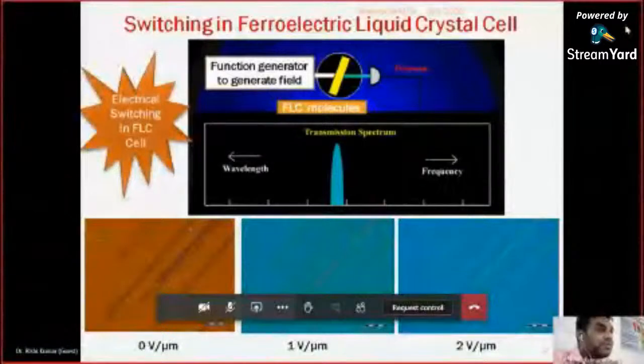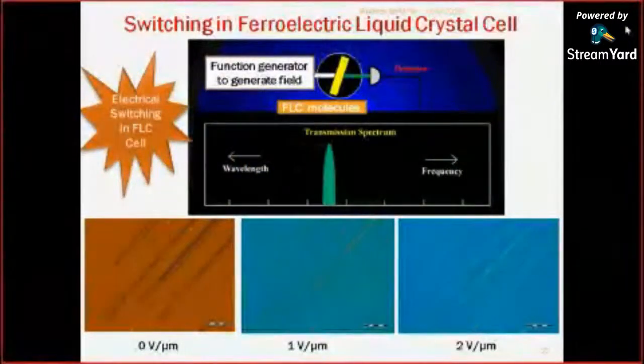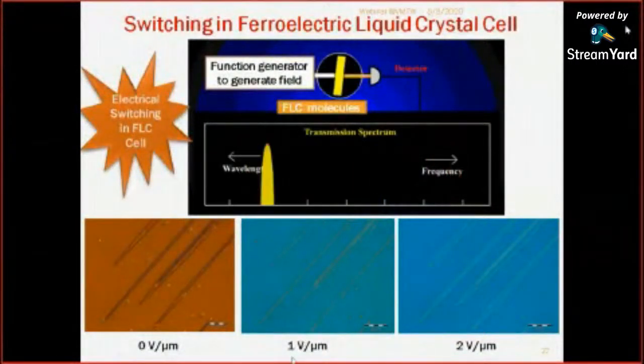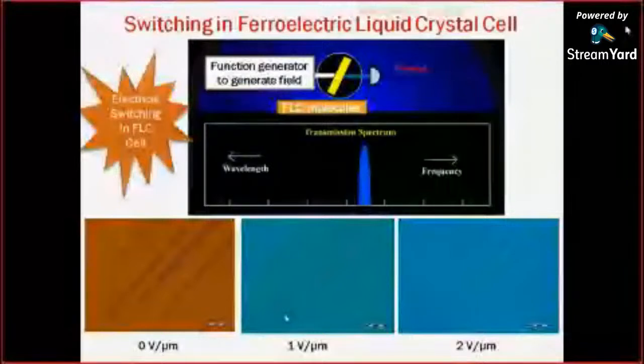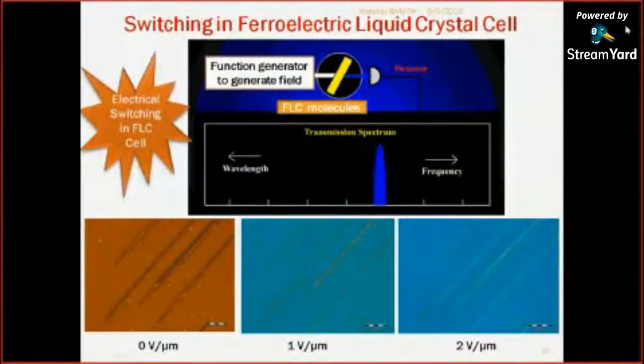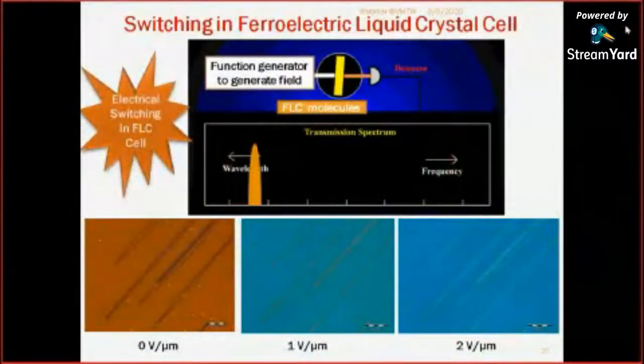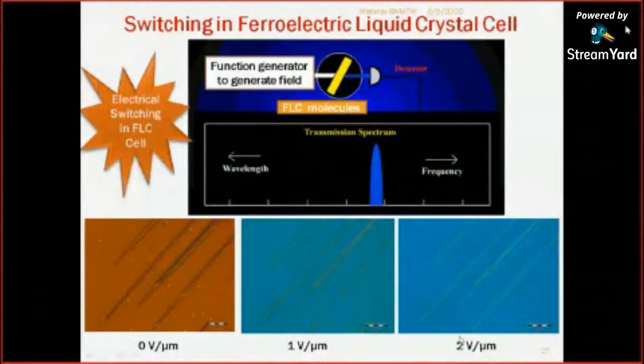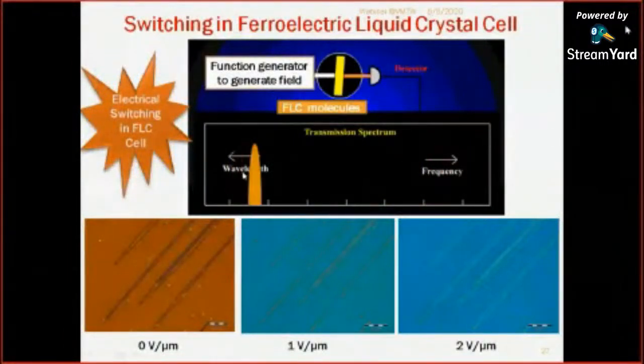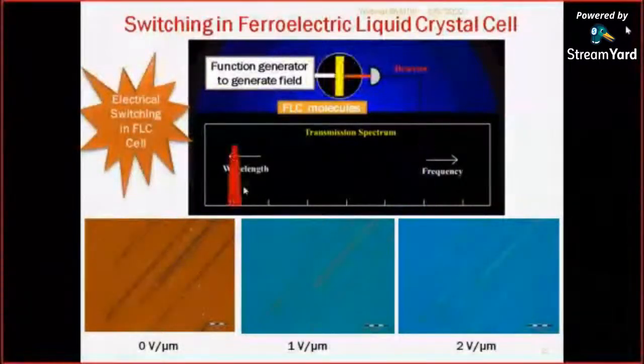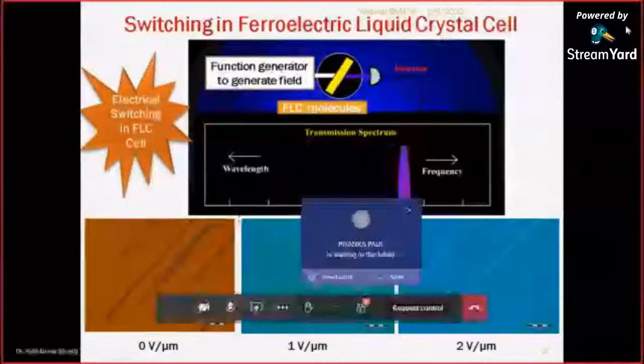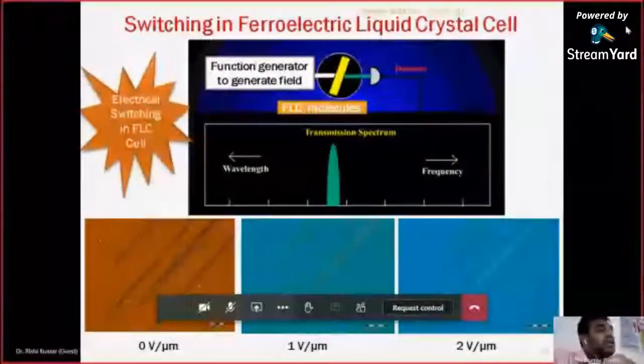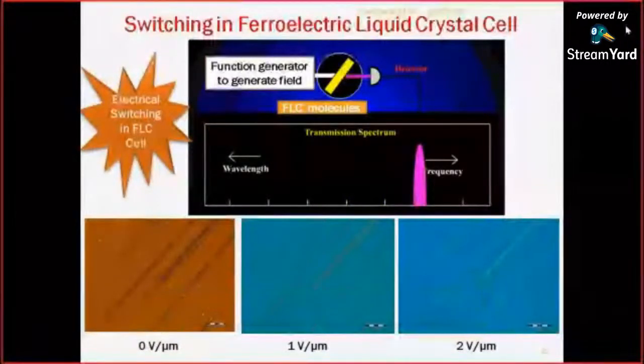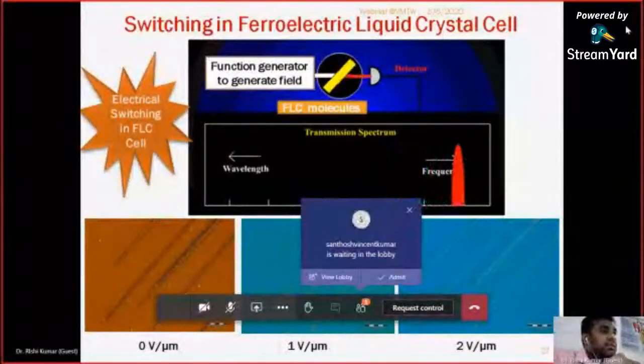So this is the switching response of liquid crystal displays with respect to voltage. Here I have applied 1 volt per micrometer, and the textures are showing different colors. This means the rod-like molecules, which are arranged in a helical pattern, show different orientation. At 1 volt per micrometer we get one orientation, and at 2 volt per micrometer we get a different orientation. That is to say, the liquid crystal molecules are rotating this way, and showing different responses toward the wavelength. As the liquid crystal molecule gets tilted, different wavelengths can be achieved, and that is the main requirement to study the optical properties of this birefringent material.